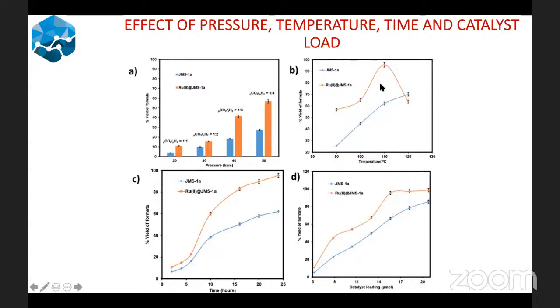So as you increase temperature, you should expect the formate to decompose to give the initial reactant. So at 120, you can see a drastic change. But of course, with the pristine MOF, we saw a gradual increase in the amount of formate that was being produced. We also looked at the effect of time.